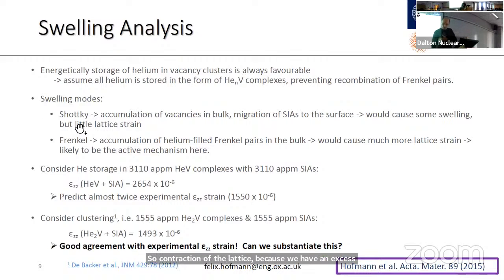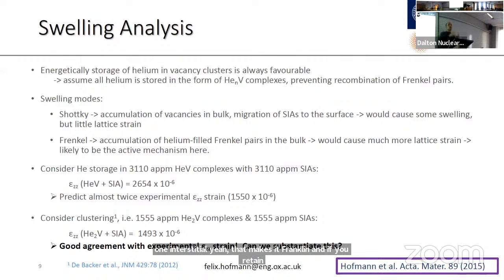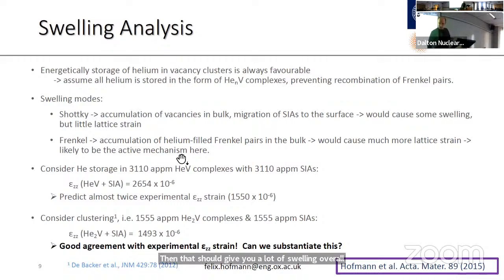Instead, the second mode we could think of is a kind of Frenkel mode where we retain both the interstitial and the vacancy that you make. So when you irradiate, you generate Frenkel pairs, one vacancy and one interstitial. That makes a Frenkel pair. And if you retain both parts of this Frenkel pair in the lattice, then that should give you a lattice swelling overall, because the relaxation volume of interstitials is large, vacancy small.